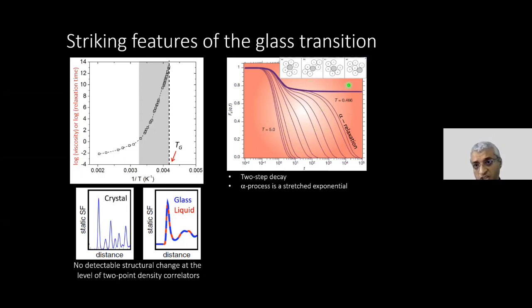But on approaching the glassy state, if I were to look at this part of the spectrum of relaxations, I don't find that it is a single exponential anymore. I find that there are multiple contributions coming about. It's what we call a stretched exponential process. So there are many exponentials coming into the process. And now, concurrent with that, if I were to look at this particular plot, this is log of viscosity versus 1 over T, and this is my Arrhenius fit, right?